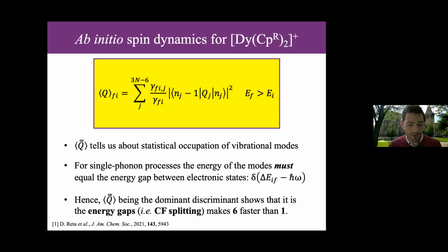Now, I point that out with great importance because we said almost the opposite thing in the conclusion of the Nature paper, that it was these specific CH vibrational modes that were so important, and you've got to persubstitute all of your carbon positions on the ring to get rid of those CH modes to make relaxation slower. And then lo and behold, that's what Layfield did, and then he made it much better. But that's not actually why it changed. It's because if you look at the coordination geometry, it is more linear, it is less bent, and the rings are slightly closer. You get a larger crystal field splitting. It is coming down to the simple answer is the right one at the end of the day. It wasn't really due to the spin phonon coupling.